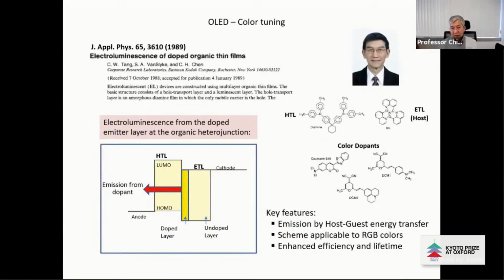The other paper that we published, 2 years later, in 1989, introduced a method to produce color, which is also very simple. We use the same two-layer structure, but we use a doped layer in the middle. The host material can be the same as the electron transport layer, but it could be different. And with this structure, you can put some dopants like coumarin, like DCM.